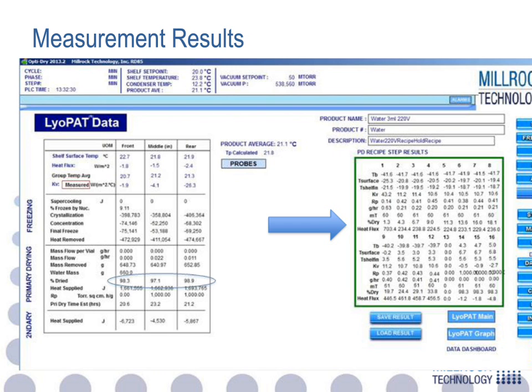And so in step 1, you can put -5 and 50 millitorr. In step 2, you can put in -5 and 100 millitorr. In step 3, you can put in -5 and 150 millitorr, and that'll save snapshots of it, and you can look at that and compare them. Then you can go and say, oh, wait, let me see what happens when I change my shelf temperature. So step 4, you would say, go to 0 degrees C, hold it, and 50 millitorr. 0 degrees C, 100 millitorr. 0 degrees C, 150 millitorr. And you can actually create a design space by doing this, where you can then take this information out and map it. Kind of a powerful tool.